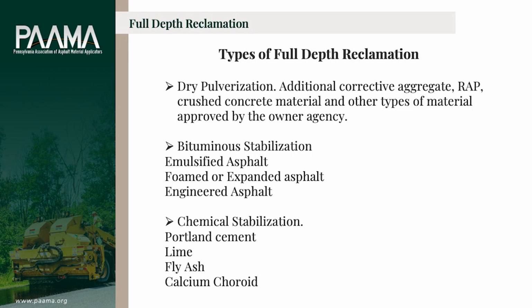You can use Portland cement, lime, fly ash, calcium chloride. Fly ash. Type C fly ash is self-cementing, almost like Portland cement. If you can get a hold of that, it's great material to use. But type F fly ash is readily available. Not many people use it. Calcium chloride, boy, that material rots your equipment away. We very seldom use calcium chloride.